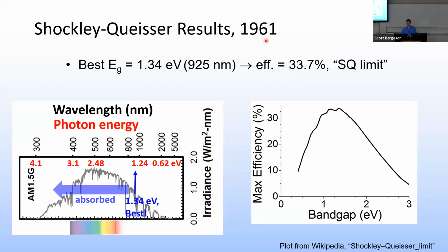So this was analyzed in 1961 by Shockley and Queisser. I don't know if it's pronounced Queisser or Queisser. Most people say Queisser. And they determined that the best possible band gap is 1.34 electron volts. This would give rise to an efficiency of 33.7%, meaning that's the fraction of energy that's turned from photons into electrons in your solar cell circuit. And at that energy, all of these photons over here get absorbed.